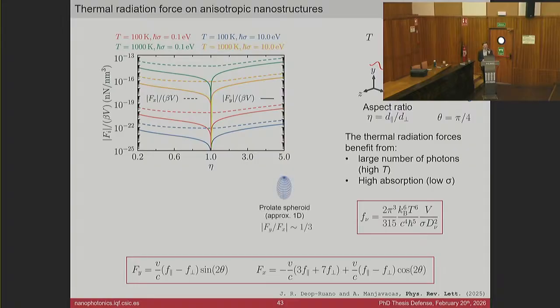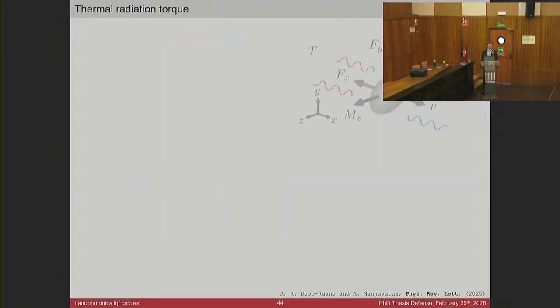Now, if we look at the aspect ratio, we can see that the ratio of the lateral force to the drag force is maximized when we have a prolate spheroid, which is approximately one-dimensional. If we move to an oblate spheroid, this is a bit decreased, and of course the force just vanishes when we have an isotropic object, which is the case of a sphere. I have shown to you that the anisotropy of the nanostructure, together with the anisotropy of the thermal radiation bath, can induce a new force, this lateral force, but there is more. That has actually been hiding here in my schematics the whole time.